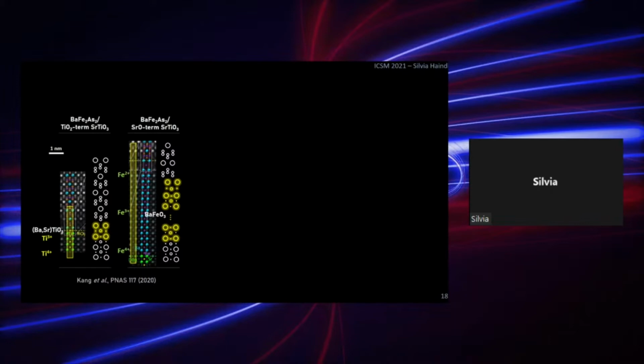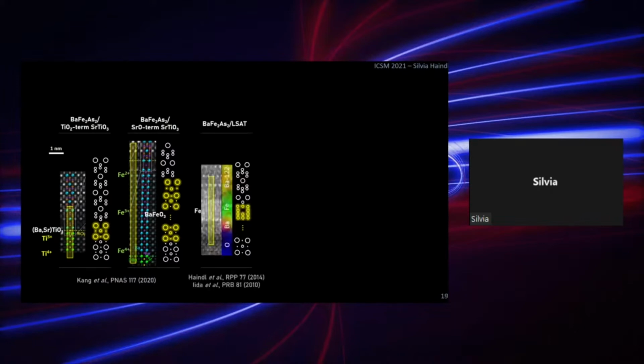We also find an interface layer reaction in the case of barium 122 on LSAT. Here the situation is a bit different. We see a metallic iron layer which is formed at the interface and some kind of barium diffusion into the LSAT. However, this interface is not well resolved.